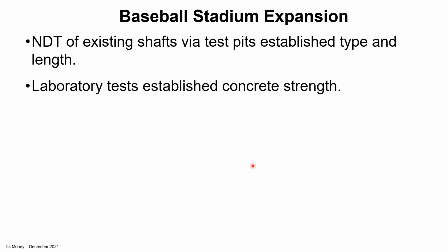A couple of test pits were dug to check on the foundations, which were found to be concrete-filled steel pipe and believed to be step taper piles. Concrete samples were taken. Laboratory tests established the concrete strength to be within the normal range. And so the team decided to do some load tests using the structure itself for reaction mass to estimate the capacity.